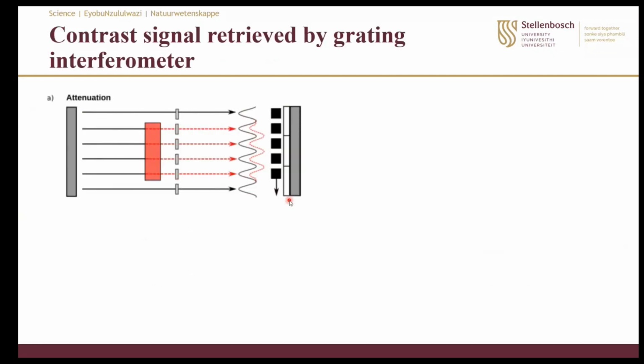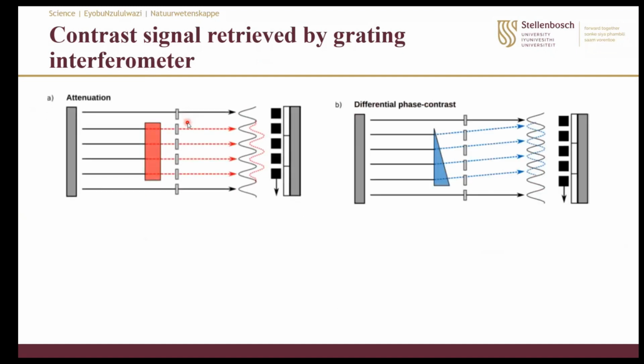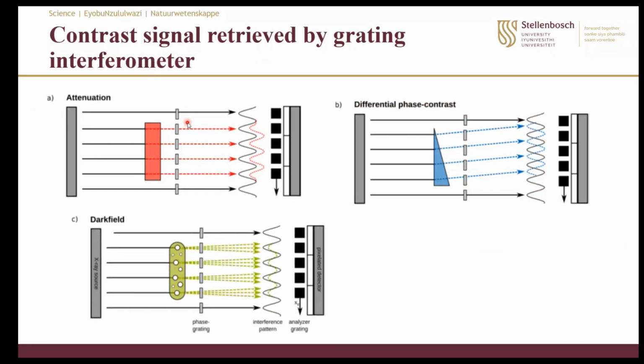And then from there, we can be having what we call contrast signal, which are in 3 forms. One of them is the attenuation, which is basically the reduction of the amplitude that results from the absorption. The second is the differential phase contrast signal, which is obtained when there's a change in refractive index, hence causing a phase shift. And then the last of it is when there is multiple scattering, then the interference pattern tends to be reduced, and this produces what we call the dark field signal.